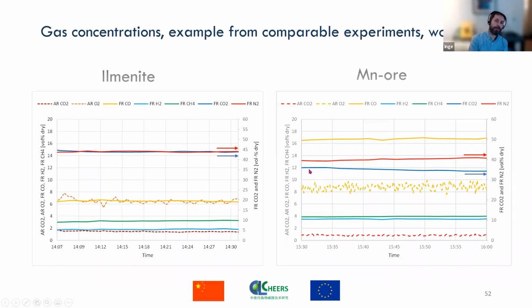And then if we look at the 2 comparable experiments with the ilmenite and manganese ore with the wood as fuel, we see the gas composition out of the fuel reactor. If we, for instance, look at the yellow curve, which is the CO, with the ilmenite we were at 6.5% CO, but with the manganese ore at quite similar conditions, we were up to almost 17%. And we also see it on the methane and the hydrogen. And this is actually in line with what the IFP found, that the gas conversion was not as good with the manganese ore.